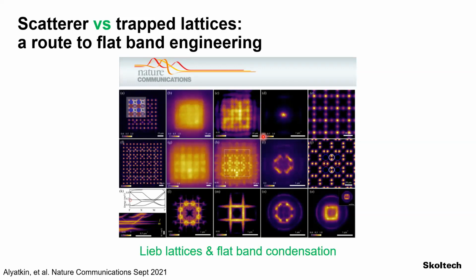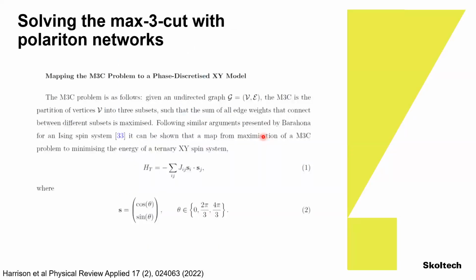But at the same time, we wanted to see if we can actually solve problems. Problems which are not interesting for physicists, but they are interesting for engineers. So what we did, we found a way to map, to discretize the XY model on a ternary basis of spins and really map the phases that we measure onto the max 3-cut problem. So, when you have a loosely connected network, which are the 3 sets that cut more of the edges between the nodes.